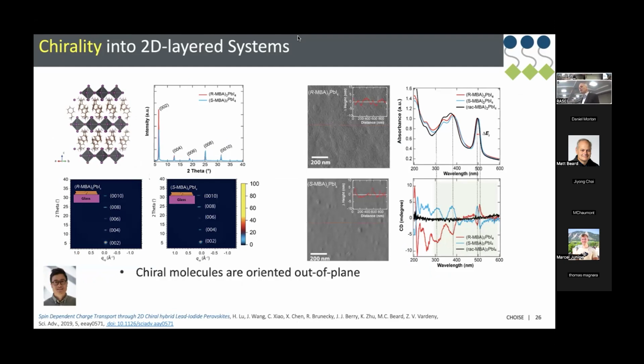One is the chiral molecules are oriented out of plane. So here's your system over here. The inorganic planes are parallel to the substrate, and these organic molecules are oriented. So everything's oriented. You have a nice oriented system. Chiral perovskites are highly textured and crystalline. So when you make thin films of them, you still get this highly textured system where the planes all arrange themselves parallel to the substrate.